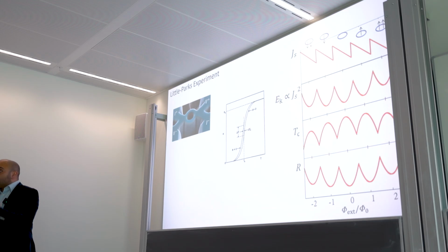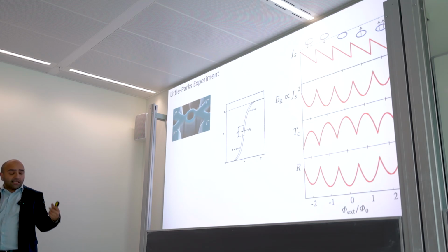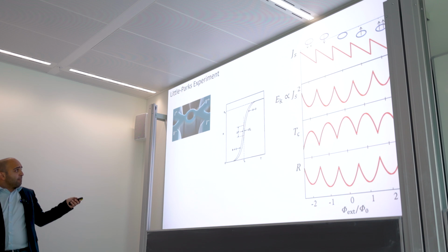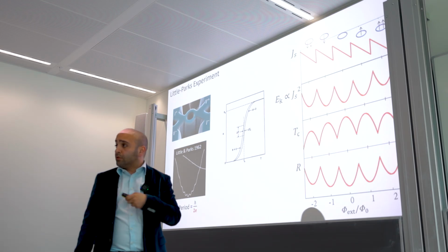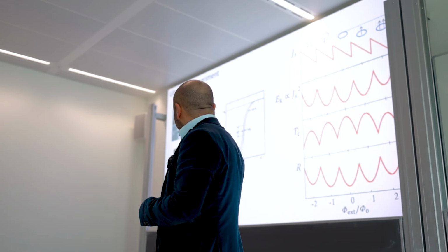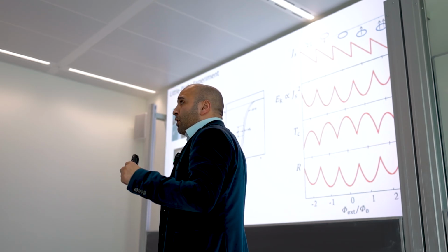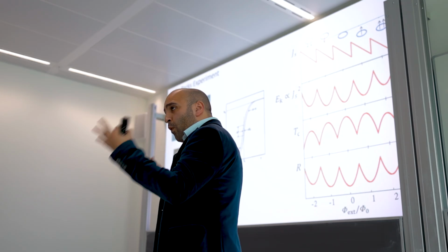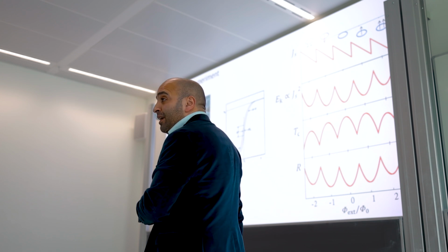So we still use this experiment for a lot of things, to show, for instance, the kind of symmetry we have in superconductors. It's a very good technique, and you'll see why, because for one thing, it's a phase-sensitive measurement, but I'll show you some more examples later. But this is actually the plot from the original paper from 1962. This is the screenshot they had. And this was a big deal when it came out, because there was only one other experiment, which was not as nice, but this was basically the experiment that established that you have Cooper pairs. Why? Because you have 2e here.